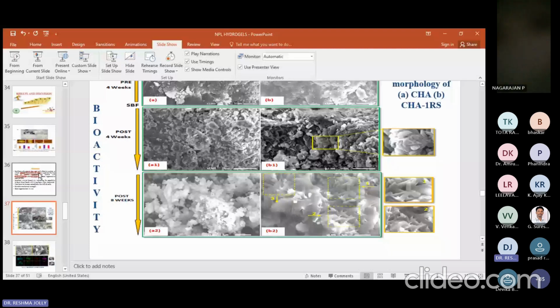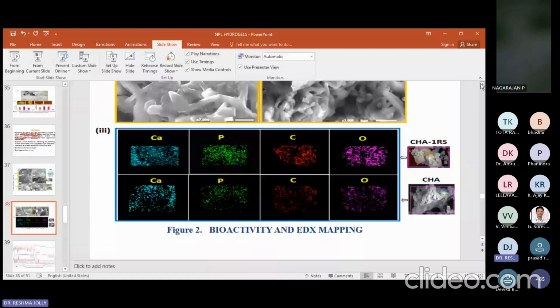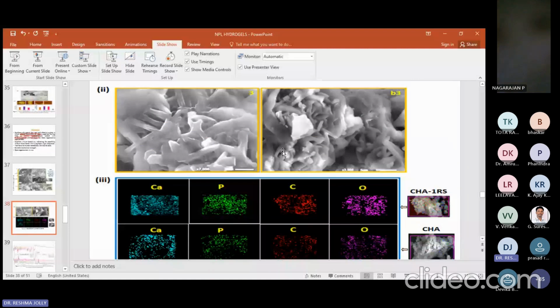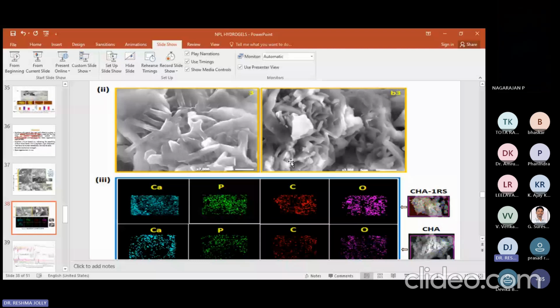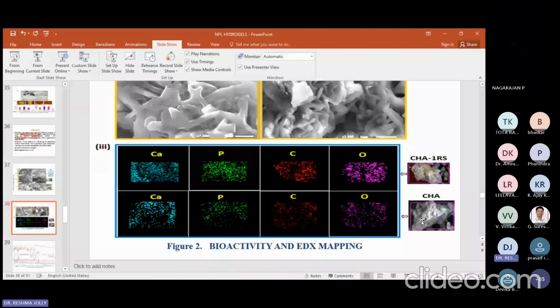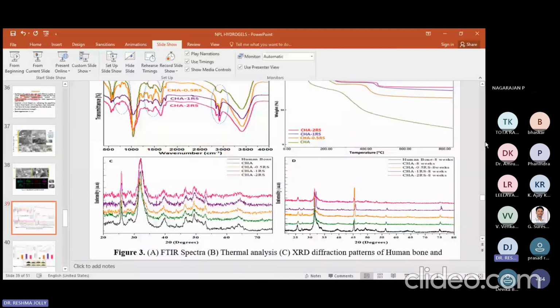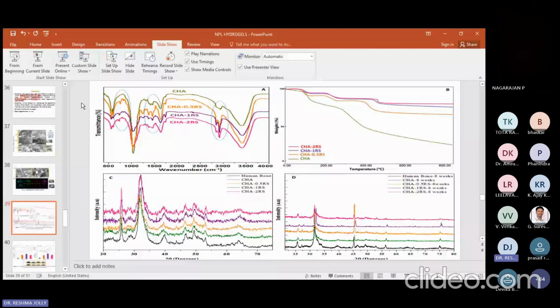So you can see the enlarged view here. Post 8 weeks, these are two images of apatite deposition in SBF. Then we performed EDX. You can see in the binary system, this is the EDX, meaning the calcium phosphate deposition we actually wanted to know. And for our material in which resin was incorporated, the ternary system, the calcium phosphorus deposition is this. Then some physicochemical characterization. This is the FTIR, in which we can find the chitosan hydroxyl peaks, the resin peaks, and the apatite peaks, the phosphate peaks, in this range.